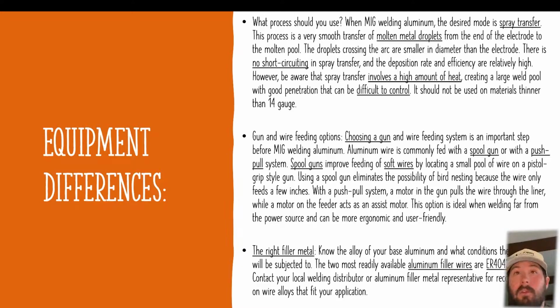A few more equipment differences. When welding on aluminum, probably the biggest difference is you're using spray transfer. So it's a smooth transfer of molten metal droplets from the end of the electrode to the molten pool. The droplets crossing to the molten pool are usually smaller in diameter than the electrode. It doesn't use short circuiting in spray transfer. The deposition rate and efficiency are relatively high, but be aware that it does involve a high amount of heat, creating a larger pool with good penetration, but it could be more difficult to control. So try to avoid using that on thinner materials at 14 gauge.